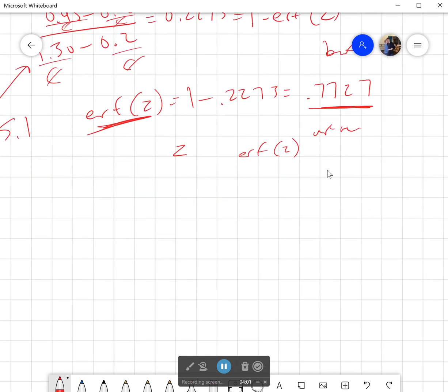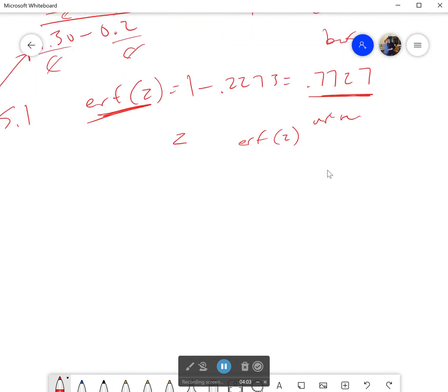So, let's look for those things right now. So, if you look in your table, you're going to find many entries and you're not going to find a 0.7727. If you did, oh goodness, you're lucky. But in this case, no luck. You're going to find 0.7707 likely and 0.7970. Just in case I haven't updated this and the book has changed a little bit. The ERF values might not change, but they might choose different Z values. And you're going to see that there's a value of 0.85 for Z here and 0.90. And we don't know what this one is.